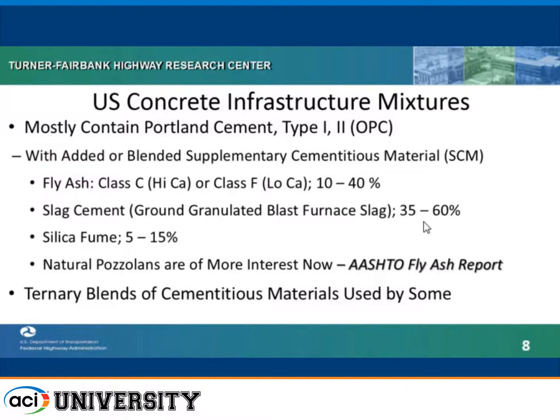This slide just sort of reviews the current situation where most concrete and infrastructure in the U.S. and Canada probably is ordinary Portland cement, but we are using quite a bit of the various different supplementary cementitious materials. Quite a bit of Class C and Class F fly ash. Many agencies are going to higher amounts of fly ash. We're also discovering that the fly ash supply is changing. What fly ashes were available in some cases are not available anymore, and you may have to go somewhere else to get them. So to some extent, agencies are switching around to different materials that they're using, and this is somewhat of a challenge. Slag cement is being used quite a bit, silica fume to some extent.